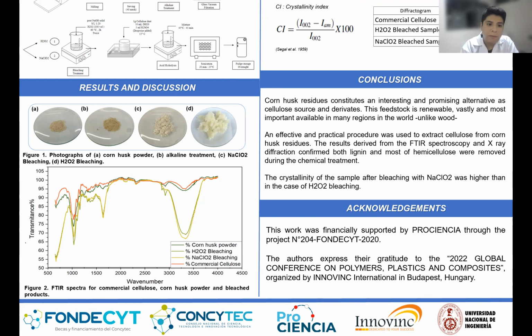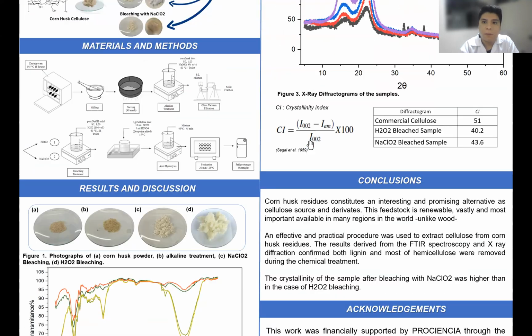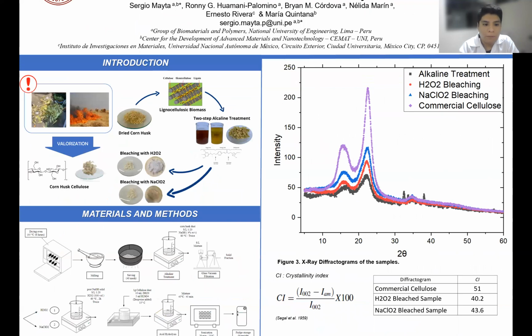Also, it is important to note that we here have strong bands at 1,636. This indicates the presence of absorbed water. This goes in agreement with the tendency to absorb substantial amounts of water that lignocellulosic materials have. So an effective drying technique must be applied, such as lyophilization or a hot air oven for several hours. Also, another technique that we used was X-ray diffraction.